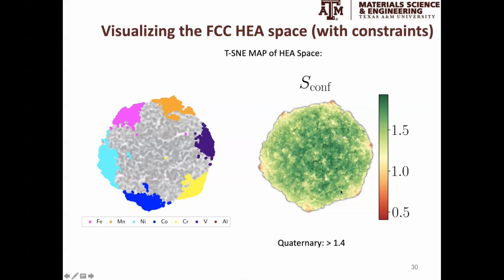Now this is the configurational entropy. The alloys at the center tend to have high entropy, and as a reference, any configurational entropy larger than 1.4 — so about here, light green — will be a quaternary or more complex alloy. So the vast majority of the alloy space in this visualization corresponds to alloys that are not binaries or ternaries.